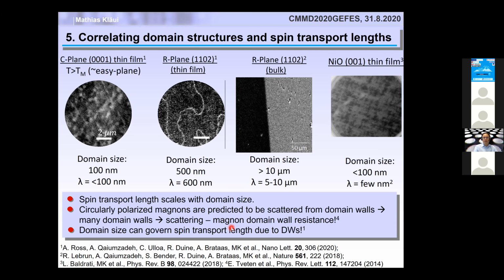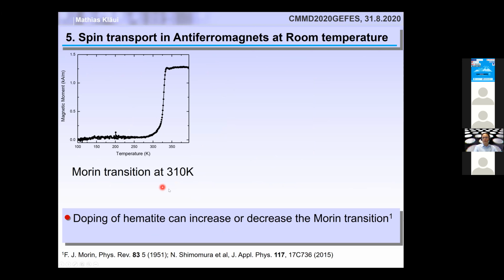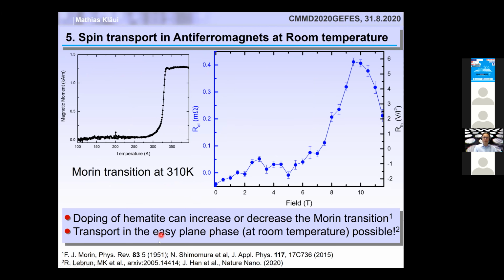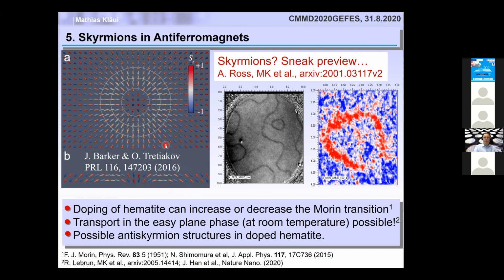And so just two teasers. Firstly, we can dope these systems to move the transition in this hematite from an easy axis to an easy plane antiferromagnet to above room temperature, and we get transport even in the easy plane phase. So there's work by colleagues at MIT and by us showing that we can actually transport above room temperature and in the easy plane phase. And secondly, we also find skyrmion type of structures. So here's the paper if you're interested, and this is now an antiferromagnetic anti-skyrmion. So this has the topology of an antiferromagnetic anti-skyrmion. If you're interested, look at this paper here for the details.